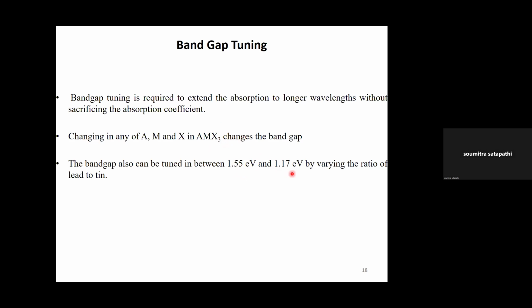Now, what is the implication of that? Why do I say it's remarkable? Because everything is related to the band gap. If your band gap is changing, your optical absorption is changing. If your optical absorption is changing, your photoluminescence is changing. I want to make an LED. So the same halide perovskite material, I can make a blue LED, green LED, or red LED. That means I can make a white LED by simply changing the band gap, which is not possible for any material so far. So that is the uniqueness.